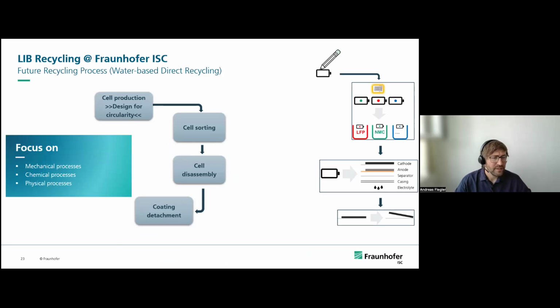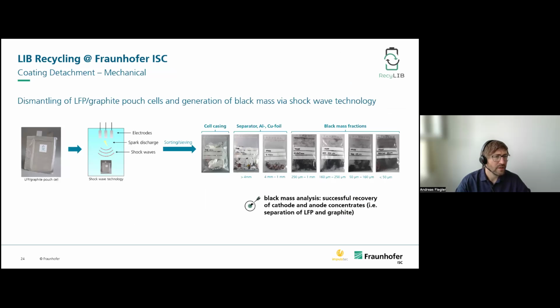For the coating detachment, here we use different methods. One is together with a partner from Germany, ImpulseTech or ReElements. Here we use the electro-hydraulic fragmentation. Then we have a reactor which is filled with water. We can put inside the cells or also production scrap or only aged cathodes or anodes. Then we have shock waves and open the cells.